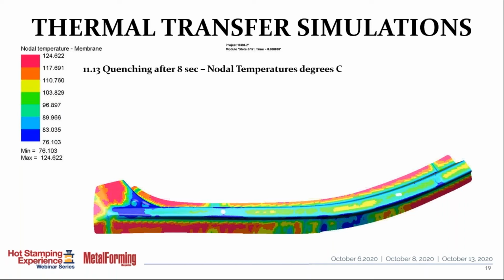What you don't know is whether, if you take the part out and you finish air quenching on a cooling conveyor, whether that part's going to twist and give you some variation, and you may need to quench it for a longer period of time in the die to get it to an even colder temperature. So part of the simulation process is understanding the quench capability.